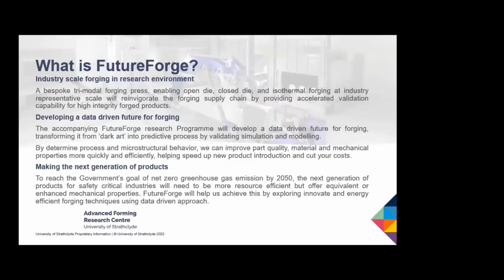The other thing that's really important about this particular system, it's trimodal. So it can do open die, closed die, and isothermal forging. So really unique piece of kit. The other important point about it is fully Industry 4.0. We have 2,000 channels of data that we can capture at any one time during the process, which is fully linked to a complete feedback system. So if we had real-time capability of predicting what was happening locally, we could feed back into the FutureForge and actually deliver a response, which would be the ultimate aim of any Industry 4.0 system.